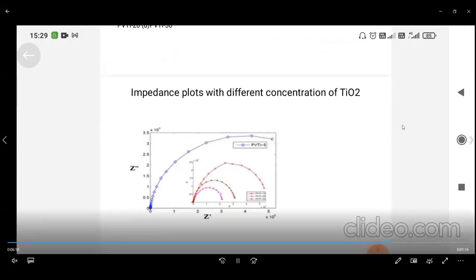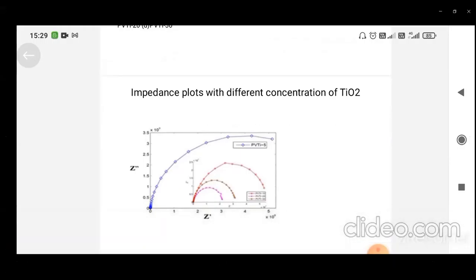With frequency of normalized plot, with a normalized frequency could be well explained by the dielectric relaxation mechanism. The semicircular observation in the impedance plot shows the bulk resistance decreasing, with the diameter decreasing with the concentration of TiO2. The bulk resistance RB decreases. The value of the frequency exponent factor remains less than 1. The decrease with temperature follows the model.